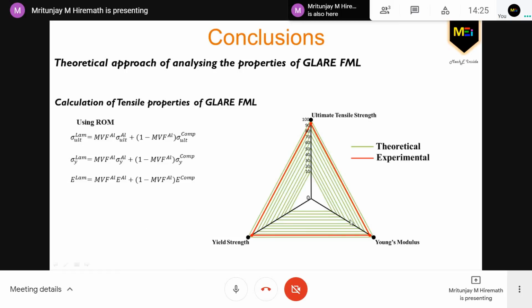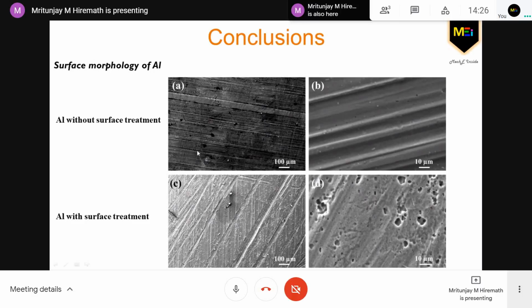And we can see a triangular shape here. What this means is that the green color indicates the theoretical values. If those were 100%, then the experimental was almost about the same as the theoretical values. So the error was less than 5% whenever these values were calculated for ultimate tensile strength, yield strength, and Young's modulus. So for the surface morphology of the aluminum, you can see how the surface appears in a scanning electron microscope